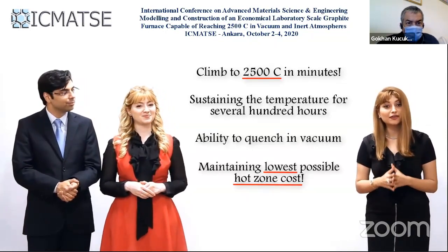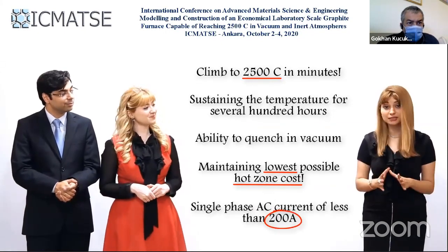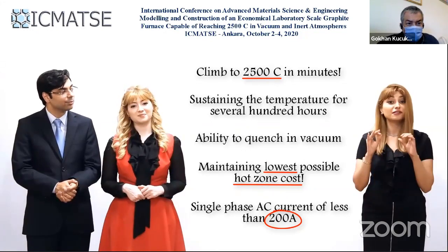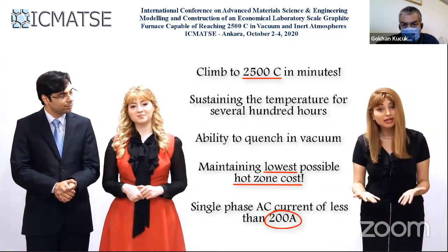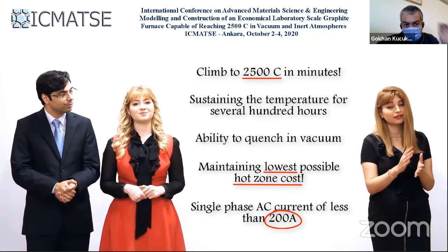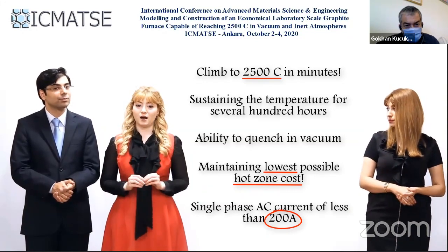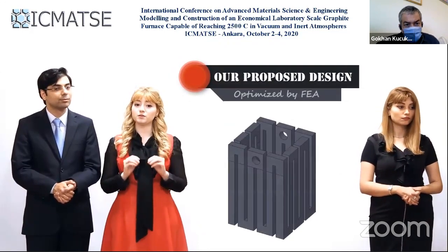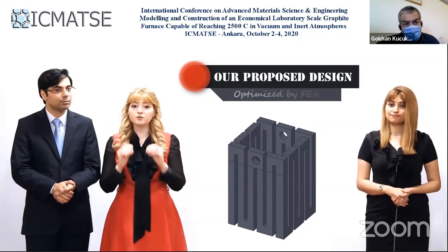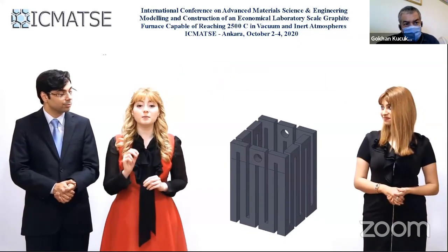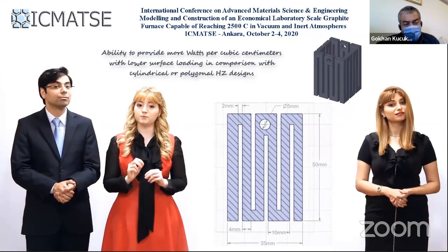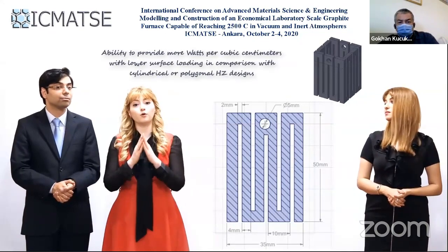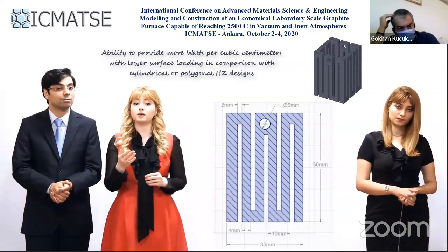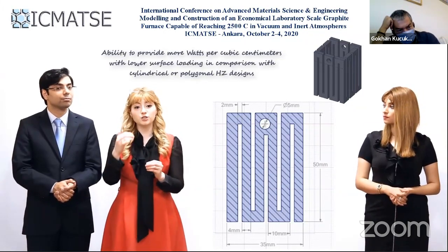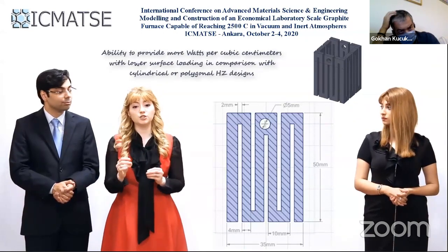We decided that the total current utilized should be less than 200 amperes, and it must be operational on single-phase alternating current, with the intention of minimizing the cost of the step-down transformer and other electrical components necessary for the system. So we tried a series of different designs which were simulated by finite element analysis, and it was concluded that the optimized geometrical design shown here is particularly interesting for a number of reasons, such as the ability to provide a higher total power dissipation by the heating element in comparison to a cylindrical or polygonal hot zone of the same volume, considering a constant surface loading value on both cases, which facilitates approaching higher temperatures and also extending the longevity of the heating element.